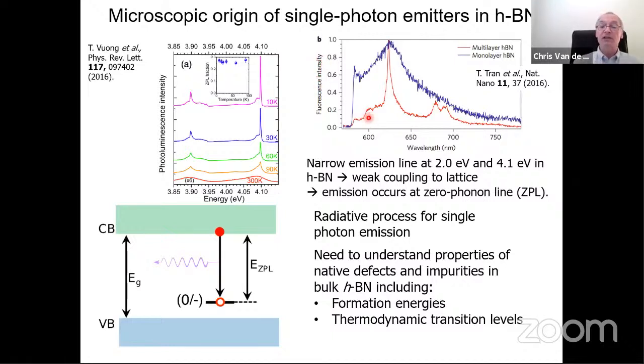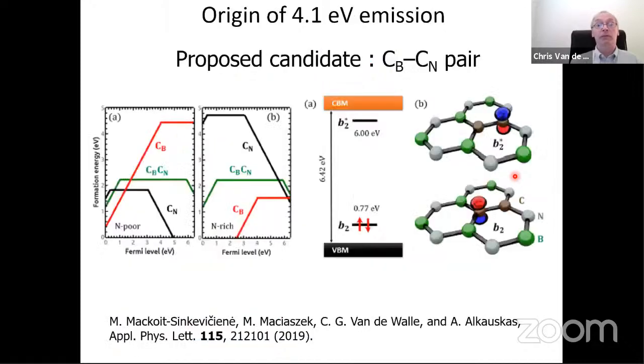There are actually 2 sets of emitters, one centered around 2 electron volts, the other centered around 4.1 electron volts. For both of these, the microscopic origin has been elusive. There have been lots of proposals, but no conclusive experimental identification. And we thought this was a nice opportunity to put our computational tools to work to help identify this microscopic origin. Okay, so I'll just conclude with showing what our proposed candidates are.